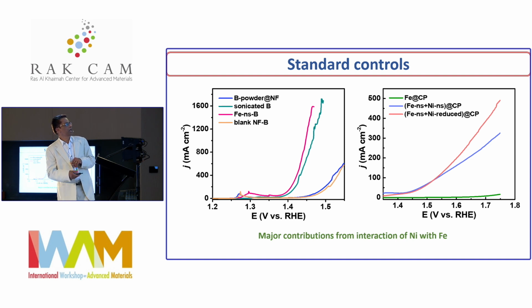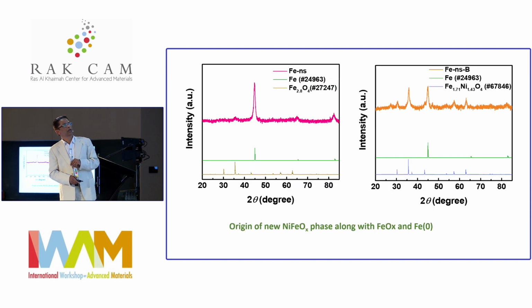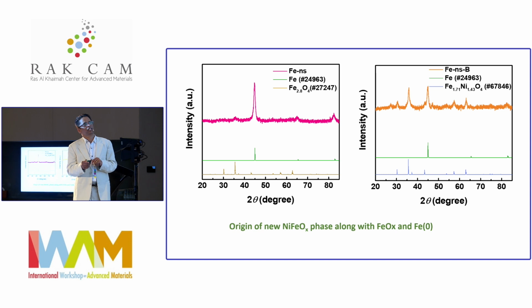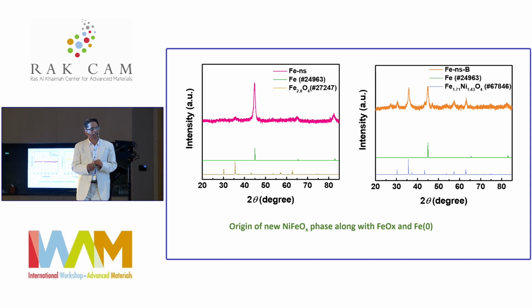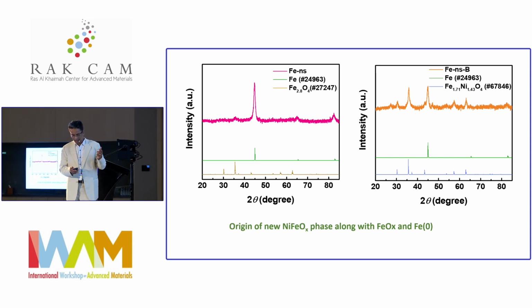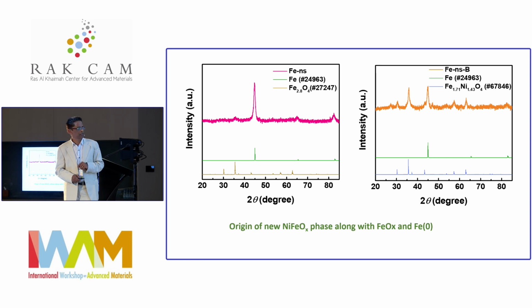And also this is a control, the same thing which we have done with the control. You won't see this kind of enhancement in carbon paper, only in the nickel, which gives that very high improvement. Another study shows that the XRD of the used catalyst shows the formation of ferrous iron, like a spinel type of structure, but it's still not yet clear what the structure is. We are still working on that to get it cleared.